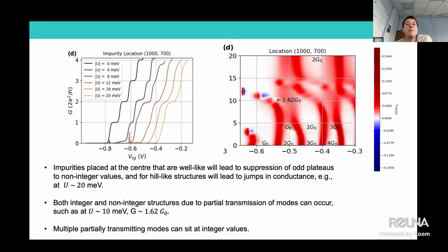When we move the impurity to the center, now the superposition of the saddle point and the disorder is quite strong. So we will see the plateaus getting affected further and further. And if we increase to really, really large values, we can see what I discussed in the previous slide, the skipping of the first plateau. If I were to have a smooth structure, this would be much more clear. And here the impurity is large enough that it is also quite clear that the plateaus are being skipped.